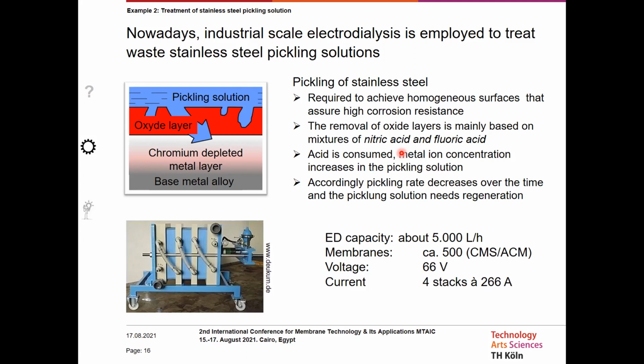Well, and during the pickling process, the concentration of these acids gets down, and the concentration of dissolved metals inside this pickling solution rises. And then there's a certain point when the pickling velocity is not fast enough, and so the pickling solution should be exchanged. Certainly, this is not the best option to discard it in terms of economical and ecological interests. So therefore, we should face recovery of the still active components of these pickling solutions. And we can remove the metals and could recover them afterwards.